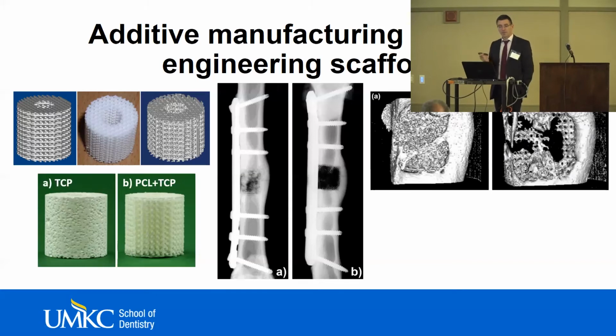But we proved the concept that we can process this material and add the second phase with selective laser sintering. And actually during the duration of the project, we managed to introduce up to 50% tricalcium phosphate. And this second phase changes the entire production process, all the parameters that you have to set. So it's not that easy. Unfortunately, we couldn't do another animal trial due to funding and duration of the project, but we would have thought that this would have performed much better in that trial.